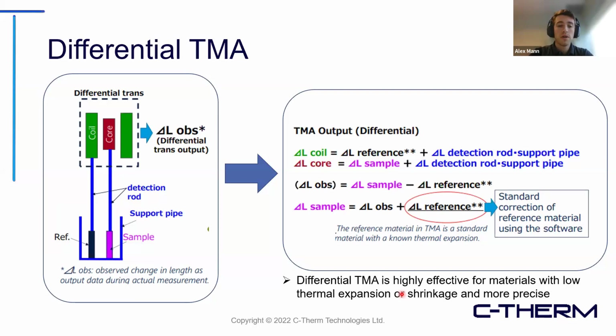So in the differential mode, the observed expansion, or what is measured, is actually the difference between the coil, which is the reference side, and the core, which is the sample side. The coil sees the expansion of the reference side as well as the detection rod and support pipe. The core side sees the expansion of the detection rod, sample, and support pipe. Then the observed is actually the difference between the two, so because it's measured on each end, it cancels each other out.